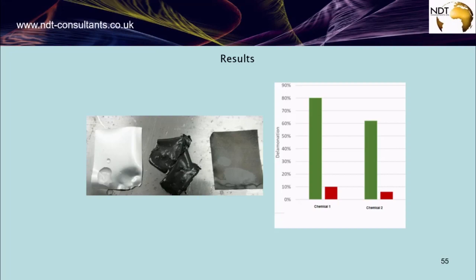So in the middle there, we have the active material, which is the mix of the valuable metals that we want to extract. And here on the right side, we have a comparison, on the green side, of the efficiency of the delamination. The green one is when we use ultrasound, while the red one is when we use just the solvent, the chemical, without ultrasound. As you can see, there is a big difference here.